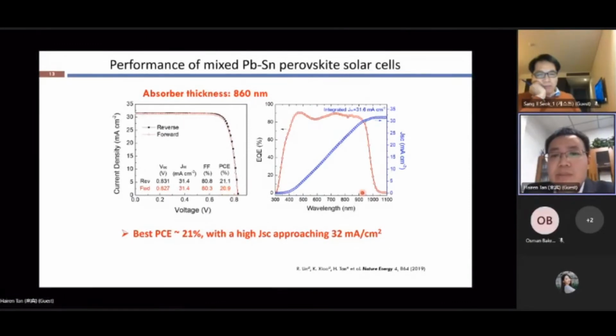And from the EQE spectra, we can see that due to the use of thicker absorber layers, we can get higher light absorption close to the band gap, and the JSC integrated from the EQE is almost 32 milliamp per centimeter square. And this is actually a big advance, especially to get a high photocurrent density.